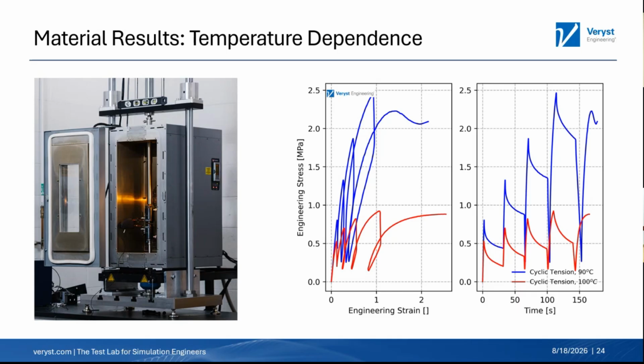And if you look at the one on the right, we're plotting engineering stress versus time. We're doing a cyclic test where we load up to a certain strain level, and then we hold that strain for 30 seconds. And then you see the stress relaxation. And then we usually do a little bit of unloading, and then we go up to the next strain level. And we repeat that. In this case, we did that for 4 levels, and we went to failure. So both of these materials failed, and that's how we got those curves.